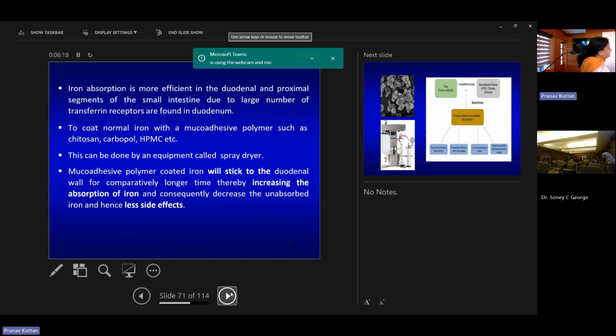Uniformly, you can get them. Then this mucoadhesive polymer coated iron will stick to the duodenal wall for a comparatively longer time, thereby increasing the absorption of iron, and consequently it will decrease the unabsorbed iron and hence cause fewer side effects. This was our hypothesis, and we checked it and we found that it works.